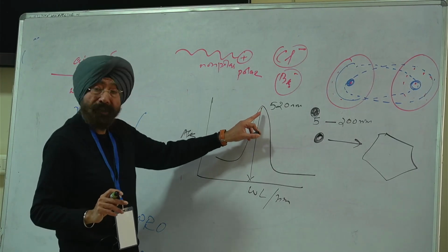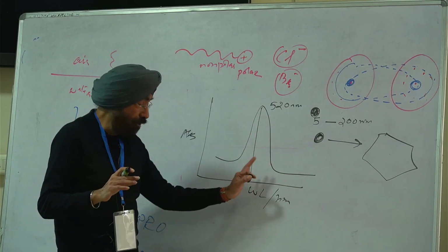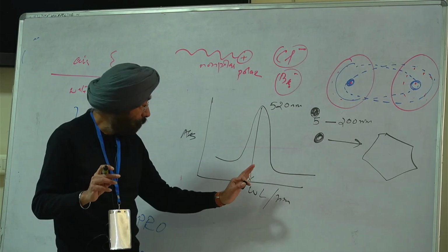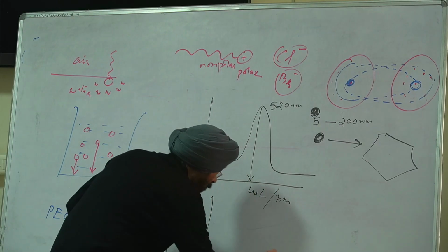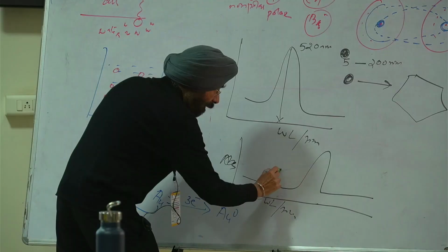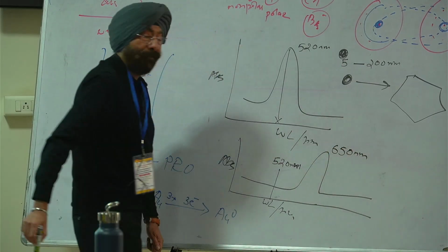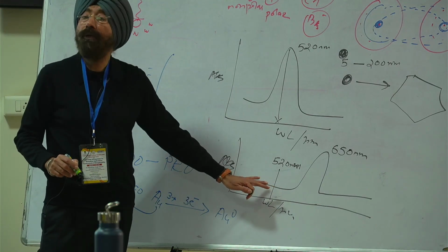That is, the peak is going to be a broader peak, or slightly blue shifted or red shifted. But if you have the absorbance like this, with wavelength in nanometers, if you have absorbance much more red shifted, instead of here it was 520 nanometer, right, and this is more than 650 nanometer, it means you have only rods. It is very hard to get only rods.